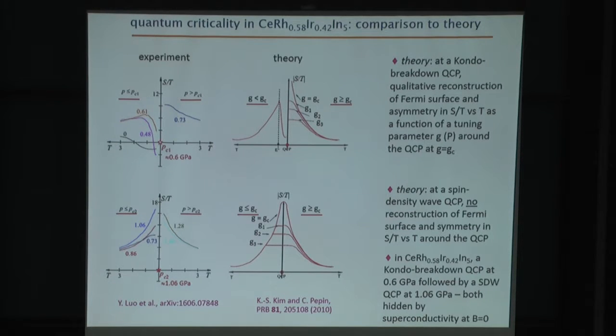So in the case of a so-called Kondo breakdown quantum critical point, she finds a pronounced asymmetry in the thermopower divided by temperature, depending on whether you're approaching a zero-temperature quantum critical point at tuning parameters that are less than the critical value, or whether you're approaching T equals 0 with values of the tuning parameter that have exceeded the critical value. So this pronounced asymmetry is reflected quite clearly in our experimental results, where now we've identified this pressure of about 0.6 GPa as being the quantum critical pressure. And so by this simple comparison of our experiments to Catherine's theoretical predictions, we would suggest that there is a Kondo breakdown quantum critical point in this material and that involves a qualitative reconstruction of the electronic structure.